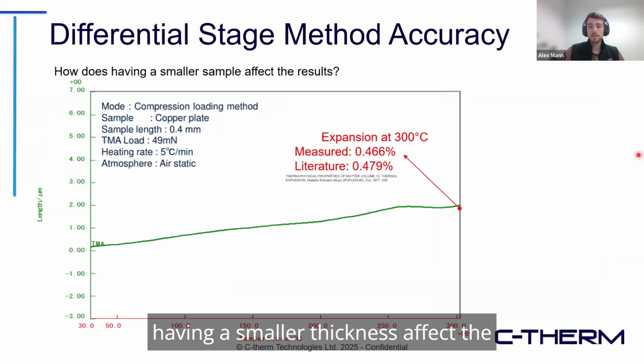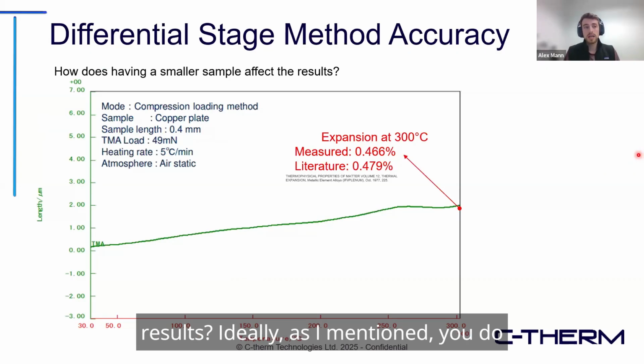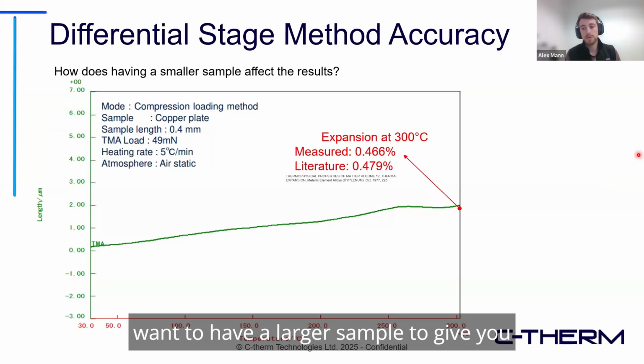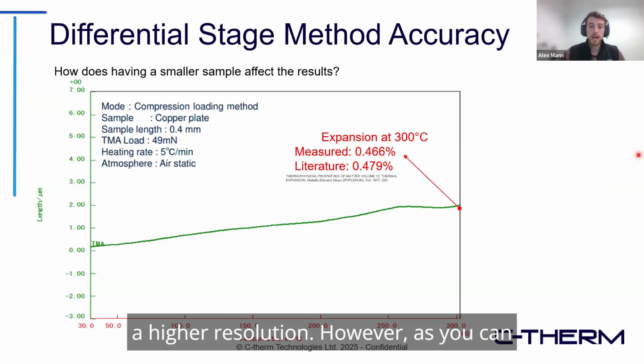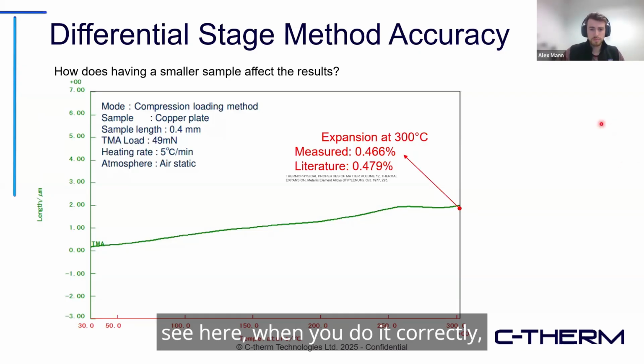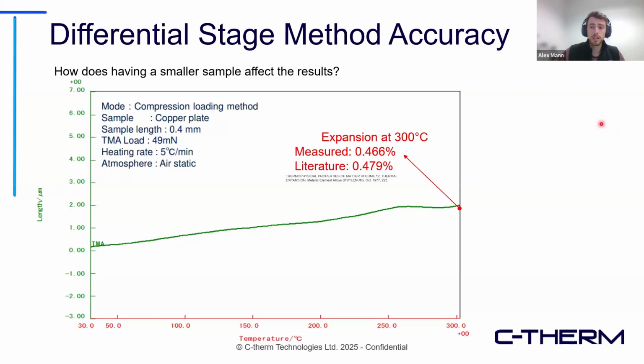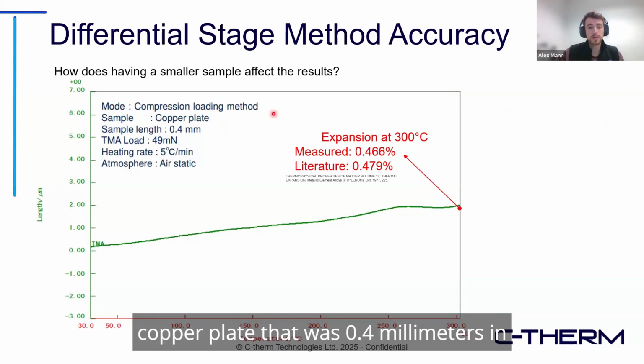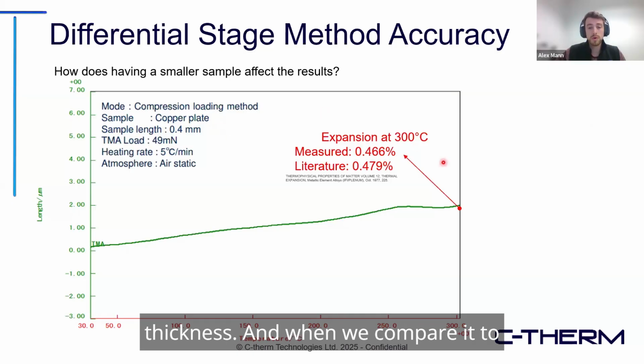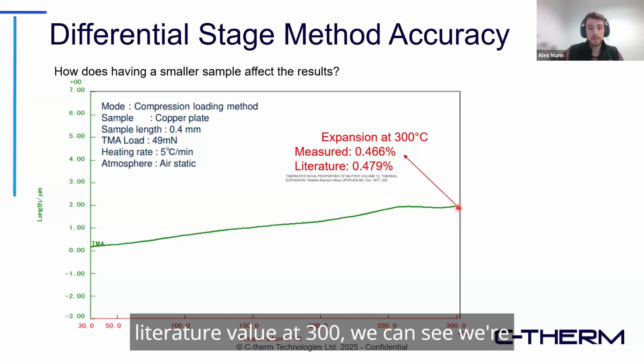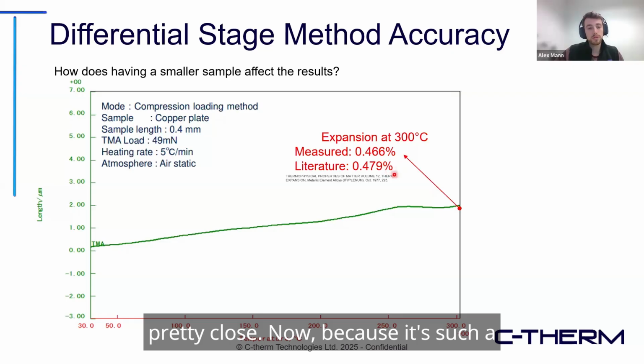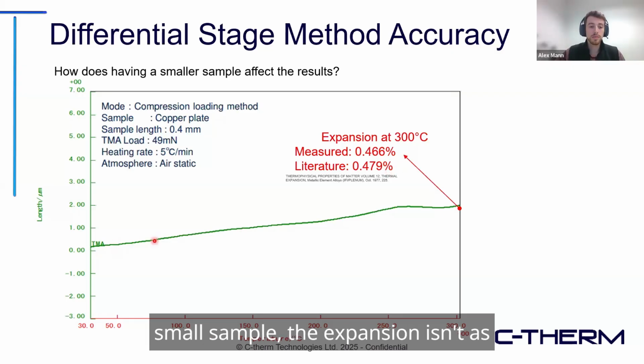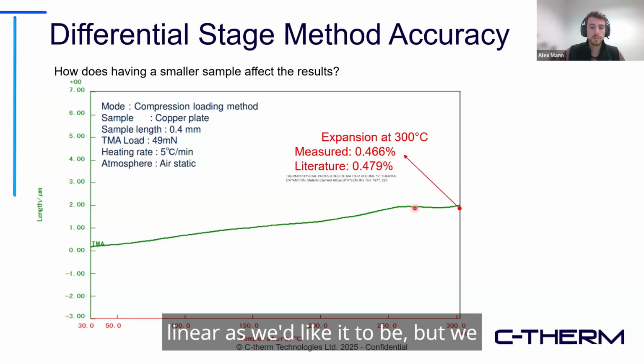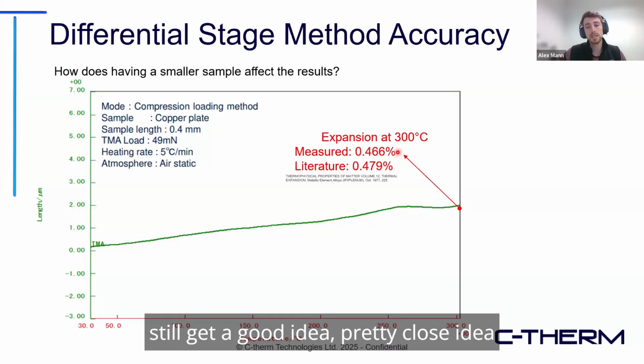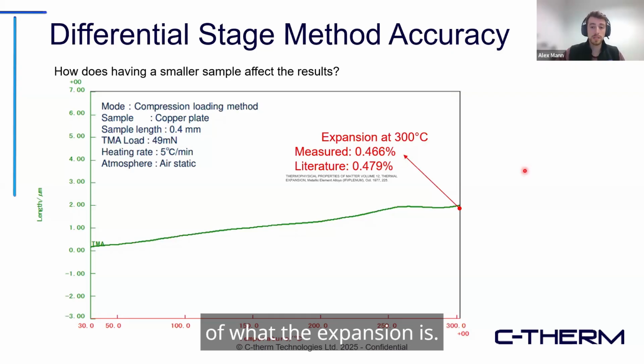Now, does having a smaller thickness affect the results? Ideally, as I mentioned, you do want to have a larger sample to give you a higher resolution. However, as you can see here, when you do it correctly, you still get great results. This was a copper plate that was 0.4 millimeters in thickness. And when we compare it to a literature value at 300, we can see we're pretty close. Now, because it's such a small sample, the expansion isn't as linear as we'd like it to be, but we still get a pretty close idea of what the expansion is.